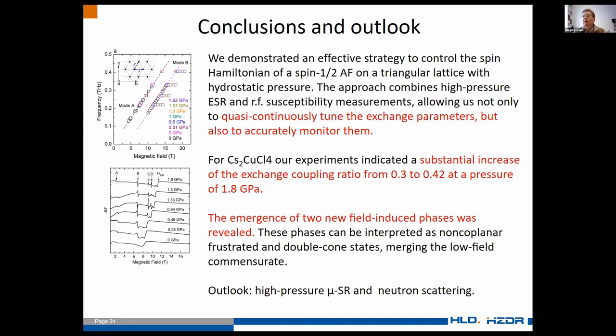Mainly we are working with bulk, because interpretation of powder can be quite challenging. But there is no principal limitation, we can work with bulk, powder, or films. For instance, for cyclotron resonance, we are using films. Two main reasons: interpretation is much more challenging for powders or pellets, and second, sensitivity. If we are using 16 Tesla DC field, sensitivity is really not a big issue.